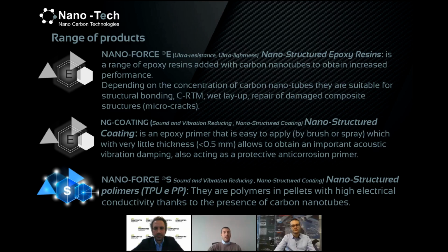Then we have a range of thermoplastic polymers, the Nano-Force S. We have two versions, TPU, thermoplastic polyurethane, and polypropylene. The polymers are loaded with carbon nanotubes in order to have a very high electrical conductivity, to be used for electrostatic discharge, EMI shielding, and sensors.